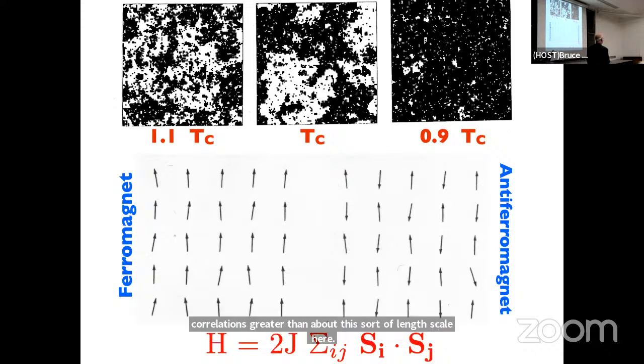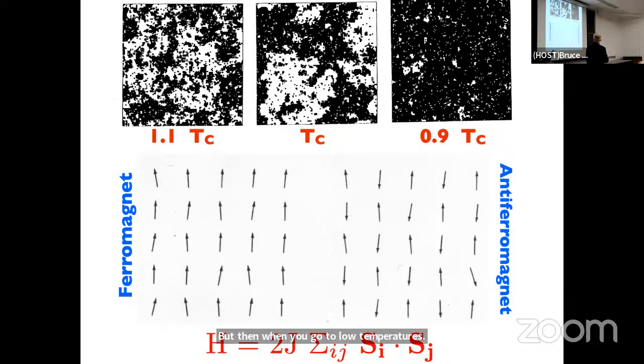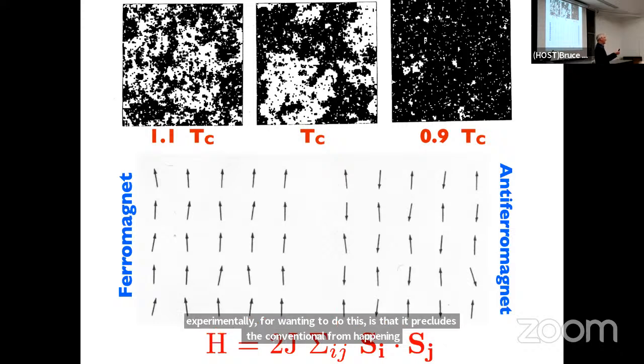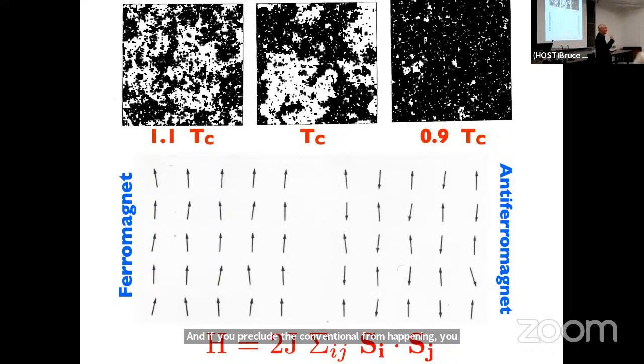But when you go to low temperatures, you break symmetry between the up spins and the down spins. There's nothing in the problem that told you to do that. The problem would be just as happy if you minimized the energy by having all spins up as all spins down, but you'll break symmetry and have, say, little islands of down spins coexisting in a sea of up spins at low temperatures. This is what almost always happens. And I've dedicated most of the last 35 years to looking for materials in which this doesn't happen. We're trying to preserve this entropy-dominated state to low temperatures. The main reason, at least experimentally, is that it precludes the conventional from happening, and if you preclude the conventional, you at least open the possibility for unconventional phenomenology to occur.